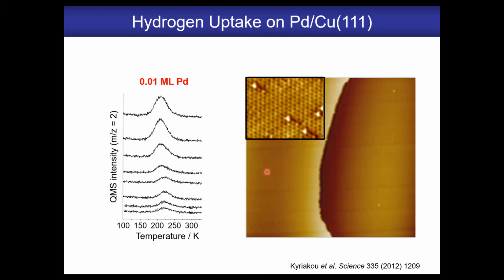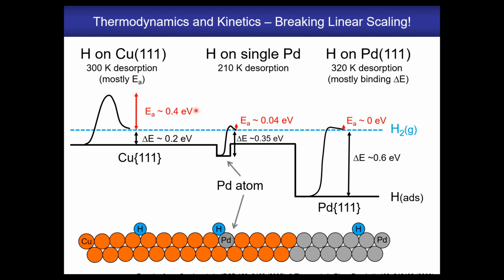And what we find is that with 1% palladium atoms in copper, you can uptake and dissociate hydrogen. And most excitingly, it actually goes on and off the surface 100 Kelvin lower in temperature than on either pure copper or pure palladium, as you see there from the desorption peak. So it turns out the energetics for dissociation and recombination look like this. You have almost no dissociation barrier, that we published years ago with one of our hosts, John Kitchen.